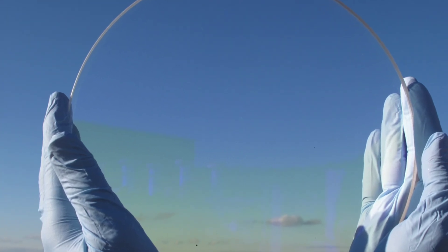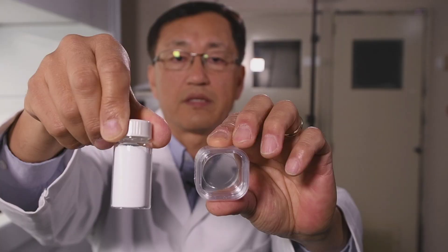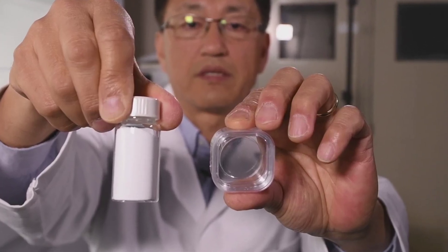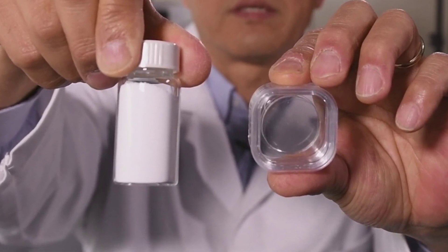Transparent armor is bulletproof glass in the simplest terms. Spinel is an evolutionary improvement in transparent armor. What we have been able to do is reduce the thickness of that armor by a factor of two by simply redesigning the architecture. Using the same materials with the same weight, we're able to reduce the thickness by a factor which has a huge impact on the weight. Spinel is magnesium aluminum oxide — an actual crystalline material that ends up looking transparent like a piece of glass.